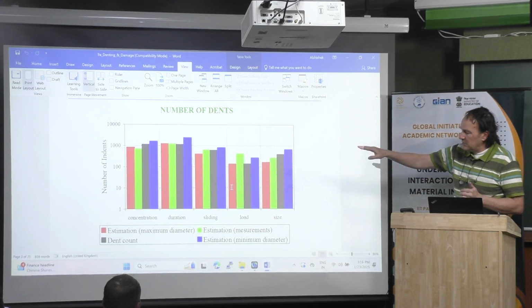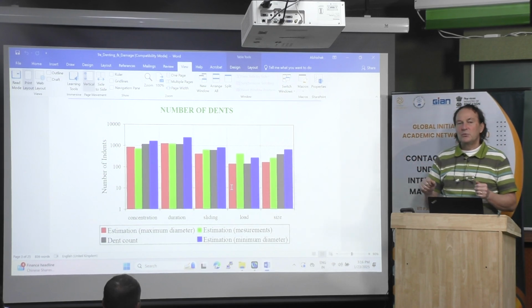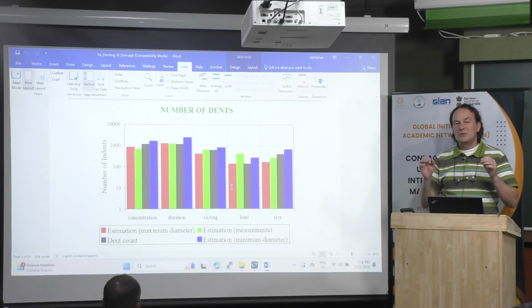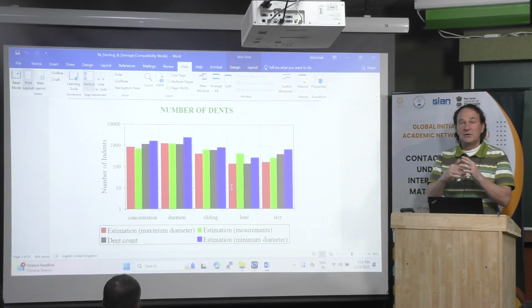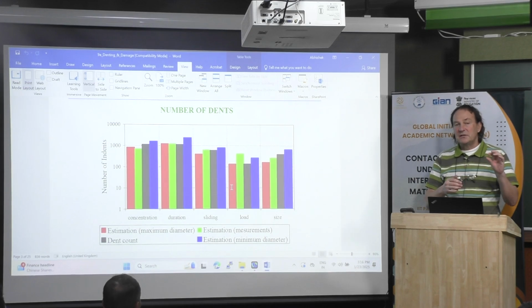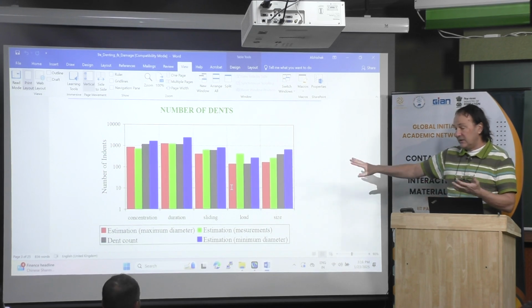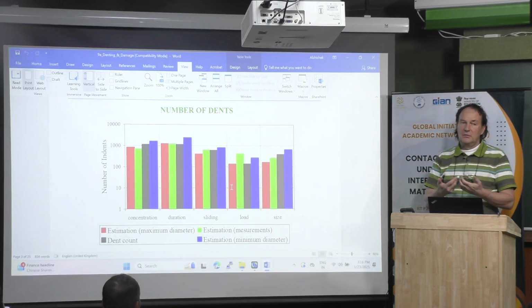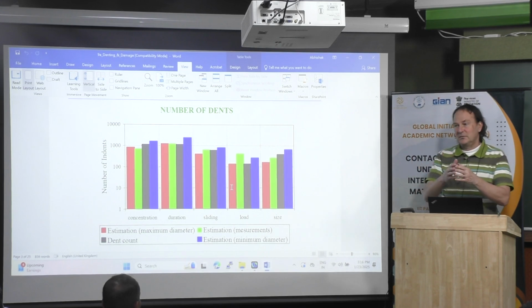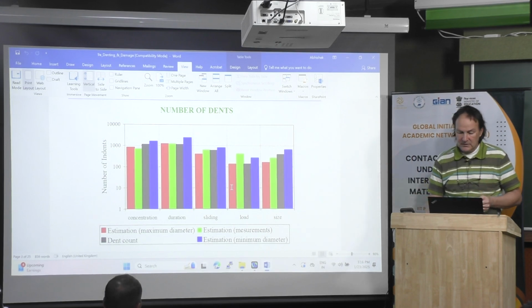Then just to explain that with that, we were able to demonstrate that when you have 1,000 particles coming into the contact, they will all come into the contact. Okay? And it will be for particles typically between 10 and 32 micrometers, and the film thickness is below 1 micrometer. Then it proves that, this is only experimental work, it proves that particles are not ejected from the contact. They go through the contact. Okay? Then this way you can dent the surface.